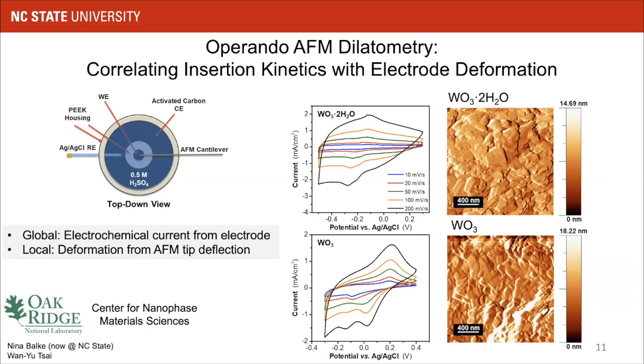It's tracking the deformation of a drop cast electrode in the middle of this AFM cell. We're able to apply an electrochemical stimulus or a bias to our electrode, globally through a potentiostat, and then measure very locally its response. This is the cyclic voltammetry that we obtain. And so again, we see more reversible proton insertion for the hydrous materials than the anhydrous materials. This is what the surface topography looks like.